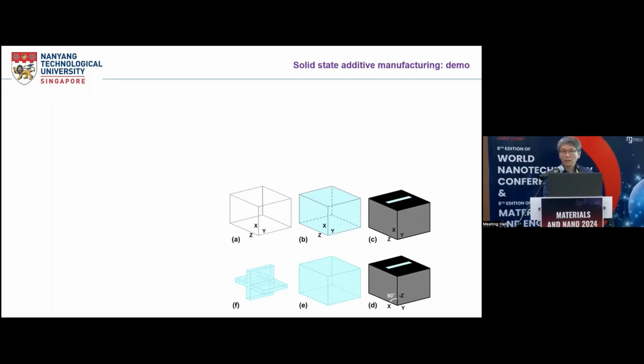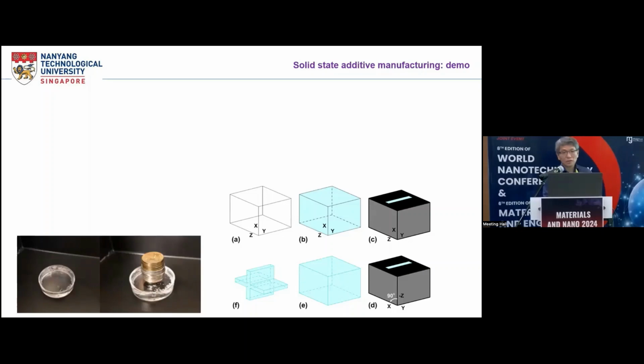And then we turn that by 90 degrees because it's not liquid, it's solid. So then we can turn that by 90 degrees and then mask on, UV crosslink again. And after that, we come out with a solid piece, and then we can cool it to wash away. For example, we can use ice water to wash away the uncrosslinked part, and then we have the shape we want.